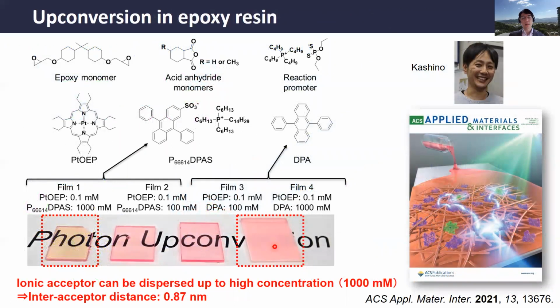Okay, the first topic of today is the epoxy resin. The epoxy resin is a very popular material as a sealing, for example, in OLEDs, because it has excellent oxygen blocking ability, or a low diffusion constant of molecular oxygen, so that you can avoid degradation. So we add the donor and acceptor chromophores directly in the epoxy material matrix. We took PtOEP, the common donor, and as acceptor, we modified the DPA with sulfonate and made an ionic liquid by ion pairing with a flexible phosphonium cation.